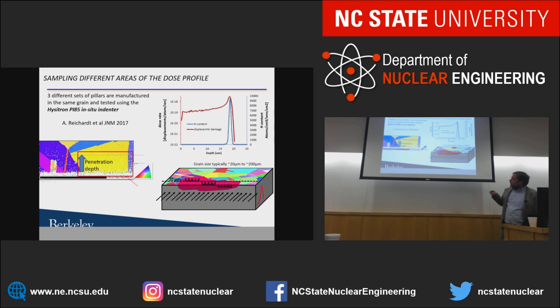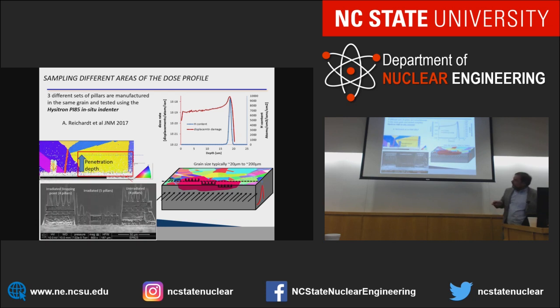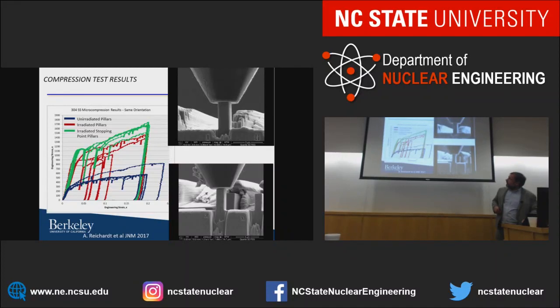You can put pillars at different distances from that surface. In reality, it looks like this. In the scanning electron microscope pictures, you have pillars here at the surface, some 15 microns deep in the material, and then some beyond 20 microns deep in the material, to study in the same grain the irradiated, stopping peak, and unirradiated material. And so when you do this in situ, you can record a movie of the deformation.